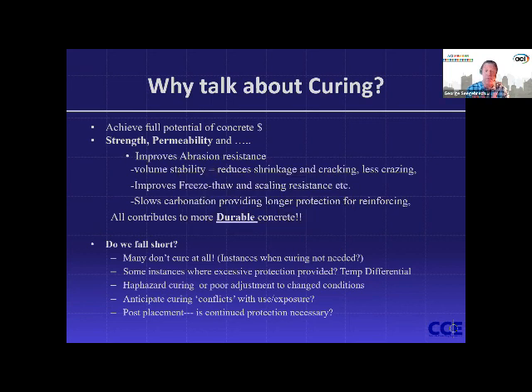I'm not going into autogenous shrinkage yet, but a standard mix is not going to start to shrink until you're done with the curing period. And so it's going to reduce shrinkage and cracking if we use that time then to get our joints where they're supposed to be, if they're sawn or if they're tooled, that they have some time to let the concrete get strength before they activate.